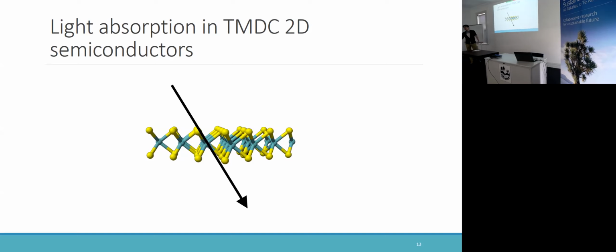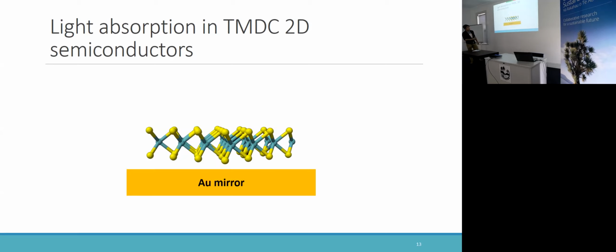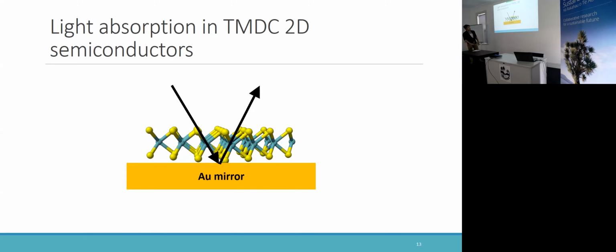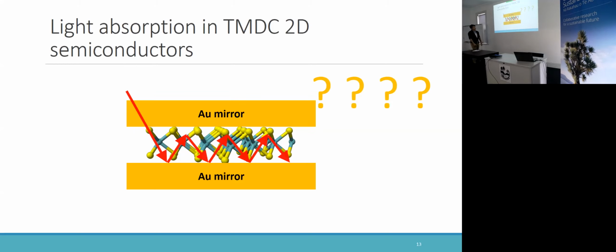So how can we enhance light absorption? One method is to place a mirror at the bottom. In this case, the light gets reflected and passes the sample twice, so maybe 20% of the light can be absorbed. So we know that if we want to enhance the light absorption, we have to create multiple reflections within the monolayers, and we can try to make the photons stay in the monolayers as long as possible. But how can we do that? Can we add another mirror on the top? The answer is no.